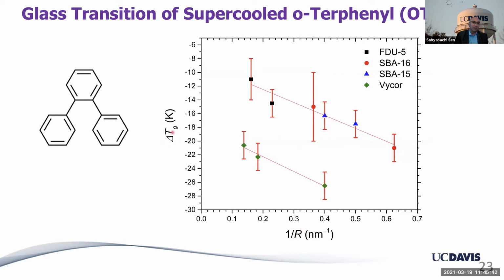The Gibbs-Thomson relationship obviously does not predict anything about TG, but a similar relationship has been reported in the literature for both TG and melting point. But one of the interesting things is, unlike water in all those pores which followed a single line, OTP follows 2 different linear trends, one in Vycor, tortuous pores, large pores, whereas straight, small pores in well-arranged mesoporous lattices. So this means that the interfacial interaction must be quite important for orthoterphenyl, not just the size effect or the pure confinement effect.